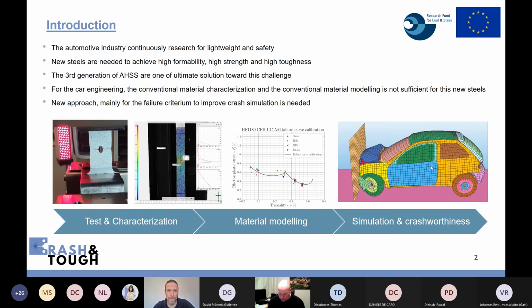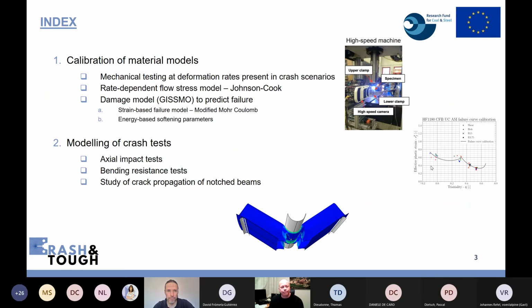So this is a motivation to, in some way or another, introduce the concept of fracture toughness in the models. So if we go through the agenda or the outline of this presentation, we will start to talk about calibration of material models, and we will also highlight the importance of having mechanical testing at the deformation rates present in crash scenarios. And we will also calibrate a rate-dependent flow stress model, in this case the well-known Johnson-Cook. And we also have used a damage model, GISSMO. It is implemented in LS-DYNA, for example, and this is used to predict failure.